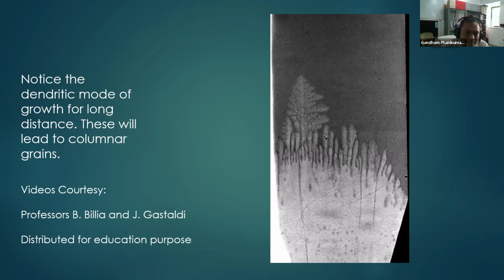It will not take place in additive manufacturing, because in additive manufacturing, the thermal undercooling is not available. I'm coming to that in a moment. And therefore, in additive manufacturing, you don't have dendrites of pure metal, but in other experiments such as casting, for example, or droplet solidification during powder fabrication, surely you will have dendrite formation of pure metals also. But it doesn't matter to us, because dendrite and interdendritic regions are identical.